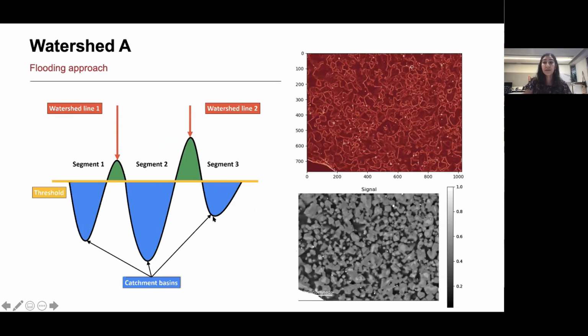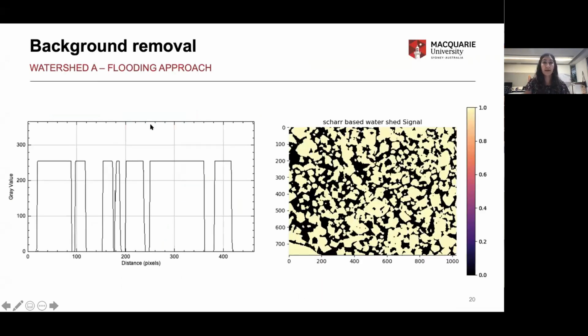And then we can just remove away that top coat, or the topographic highs, which would correspond to the background material. So this is really good if you've got an image which is noisy or has background material that you're not interested in. It would also be really good where you have more than one mineral that you're trying to analyze. If you have two or three different mineral modes, you can assign them different grayscale intensity values, and this will help you remove the background away. Following that background removal and the flooding approach, we can see the grains now have much better grayscale contrast, and it's really clear where we have these grain boundaries because our grayscale values have fallen completely to 0. All that we're left with is the outline of our grains.